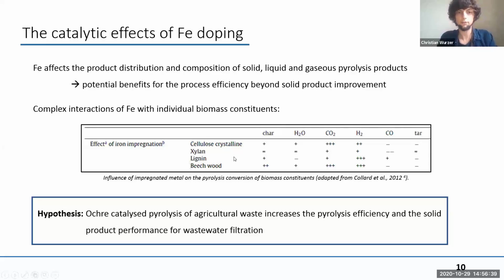However, in this table, the interesting thing is you have these three main constituents, cellulose, hemicellulose here as xylan, lignin, and then a complete biomass. And on the right, you can see the estimated change in pyrolysis yield: whether the char yield increases or decreases, the amount of water in the gas phase, CO2, H2, CO, or the tar fraction.